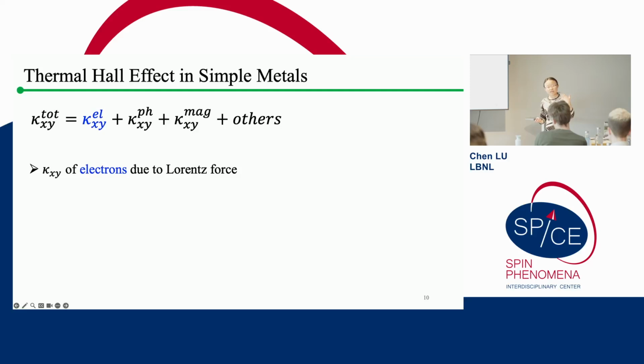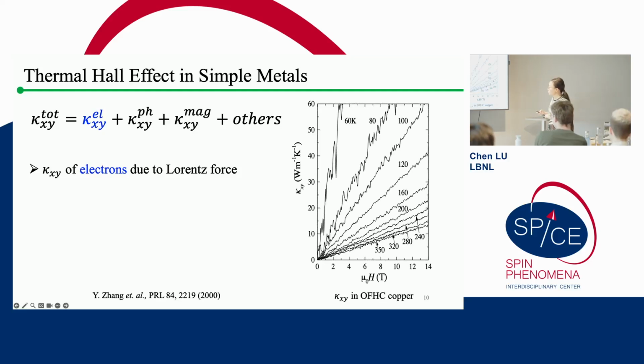Because when the electrons propagate inside a magnetic field, because of the Lorentz force, they can give you a Hall effect. So electrical Hall and thermal Hall correspond to each other. So one thing I'm going to show you here is basically the thermal Hall effect measured in oxygen-free copper, which is one of the most simple types of metal materials. You can see what has been plotted here is the thermal Hall conductivity kappa xy versus the magnetic field. And you see in copper, it already has a very large thermal Hall effect along all these different temperature ranges.